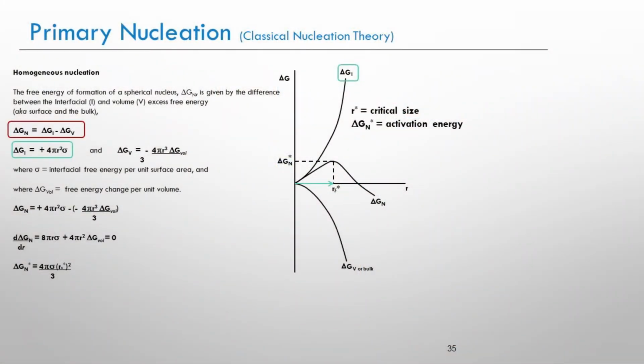And the classic nucleation theory, which, there are other nucleation theories out there, density fluctuations and the like, but to be honest, it's still one of the most practical descriptions of nucleation processes. Typically, you'll break down the energy of the nucleation process into two separate terms. The initial term that is disfavorable is associated with interfacial tension. And then there's this other term which is associated with volume growth of the actual crystal.